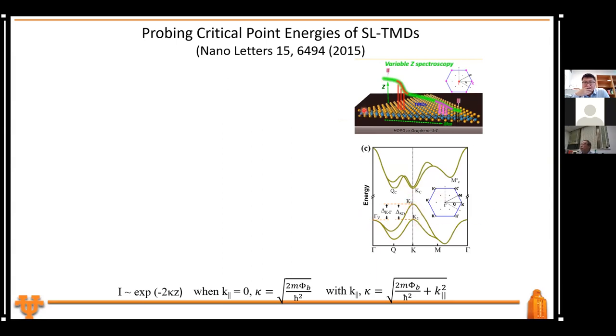So if you hold a constant tunneling current, then your tip to sample distance is going to adjust itself closer to pick up the states here, because now the kappa is a lot larger. So you will automatically reduce the Z to pick up the state. Then after you finish this, you pass through the valence band maximum, then the tip will push further in to pick up states from the underlying graphite.